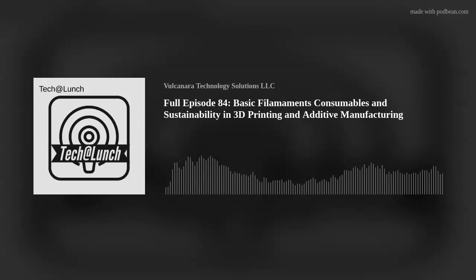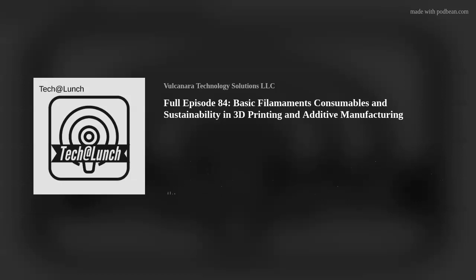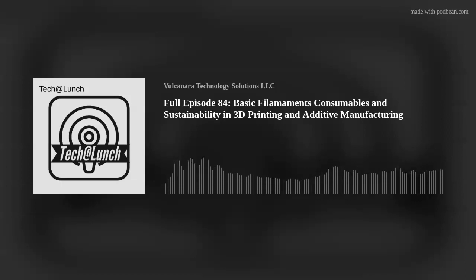PETG is my main go-to everyday filament. I use ABS if I want something temperature-resistant that I can leave outside without degrading in the sun. There's a process called vapor smoothing where you take acetone — just a bottle cap's worth — put a paper towel down, wet it with the acetone, put it over the cap, place the print on top, enclose it, and give it 20 minutes to a few hours depending on the print size.